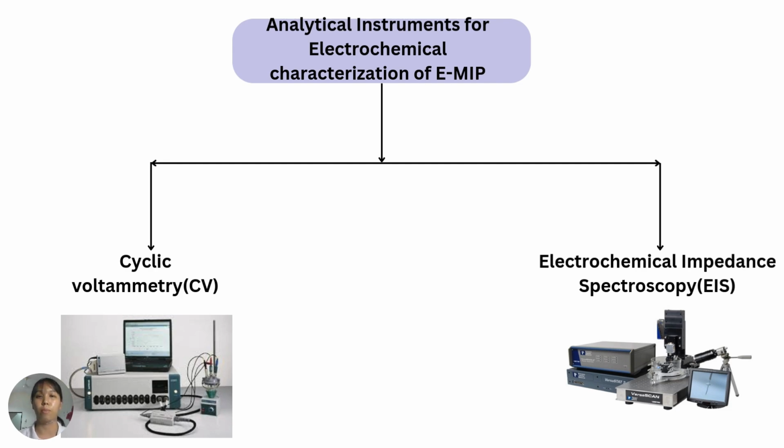In CV, we use potassium ferrocyanide as the redox probe to examine the alteration in the electrode behavior following each stage of sensor assembly. The reversible redox reaction of the redox couple can be utilized to investigate the electrochemical performance of the bare electrode or also the modified electrode.